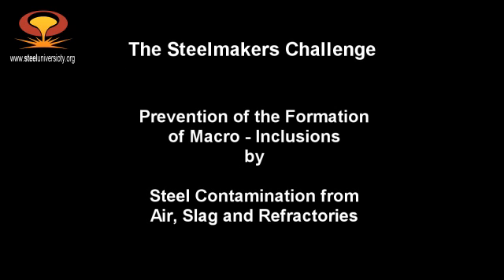In conclusion, the steelmaker's challenge is to prevent the formation of macro inclusions. These inclusions can be formed by steel contamination from the air atmosphere, by slag that is drawn by vortexing from one vessel to another, or by refractory erosion. All of these sources — air, slag, or refractories — result in the formation of macro inclusions, and the challenge is to prevent this kind of behaviour taking place.